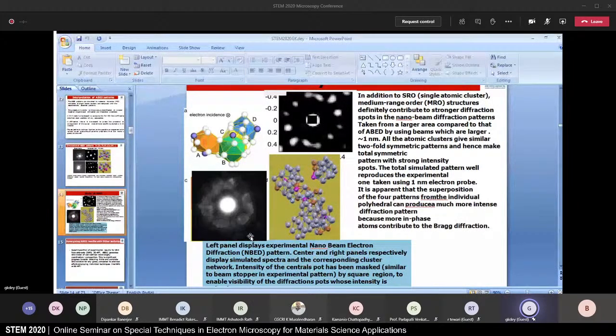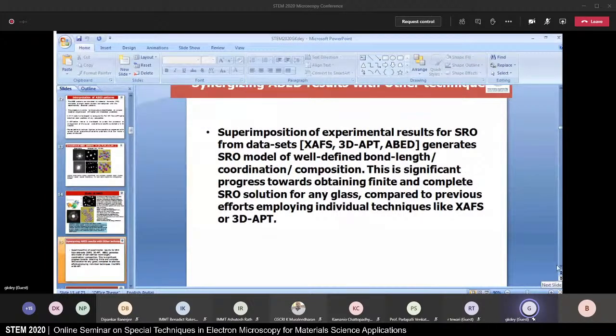So just to summarize this ABED part, angstrom beam electron diffraction, we could see how we can get information about a cluster. We could also see how the two clusters are joined, so that you get a good diffraction pattern from the two adjacent clusters, and tell how these two clusters are joined. That means you are building from short range to medium range order, and you will see that this kind of information could not be achieved earlier by using tools like XAFS or 3D atom probe tomography.